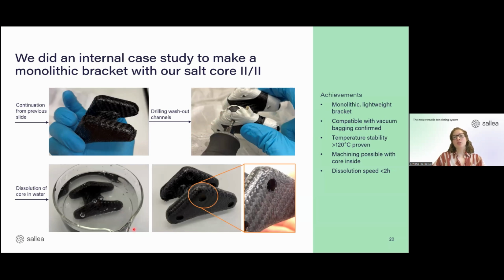The dissolution took roughly, I think, 1 or 2 hours for that part when it was just being left in the water. And then here you see the resulting part. I know it's a bit hard to see, but it's really hollow inside and it's super light. Maybe here you see it a bit better, that there is really nothing left inside. And what this proved is that we can achieve monolithic lightweight bracket parts with our salt cores.